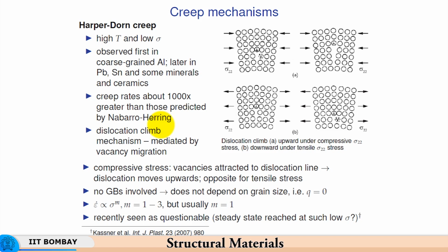But the creep rates are 1000 times more, meaning there is one more mechanism operating, which means that a dislocation climb mechanism is operational, which is aided by the vacancy migration. So, there is one more mechanism coming into play, in addition to vacancy diffusion, it is vacancy migration.